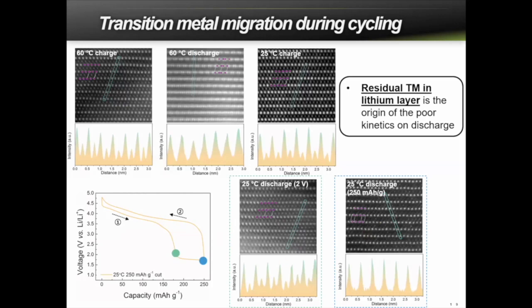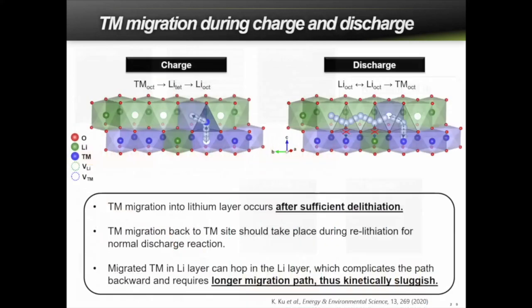And the series of pictures imply that the lithium intercalation and deintercalation in this lithium excess layered material is strongly coupled with the transition metal migration. So according to these observations, we propose a new lithium intercalation and deintercalation mechanism coupled with the transition metal migration in the layered structure. First, during the delithiation, the transition metal can easily pop up. Okay, so these are the original transition metal layer, and these are the original lithium layer. With the charging, with the delithiation of lithium, this transition metal can easily pop up to the vacant lithium layer, and the transition metal should migrate back to the transition metal site during the relithiation for normal discharge reaction.